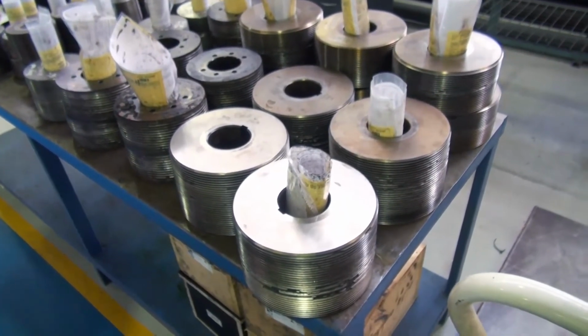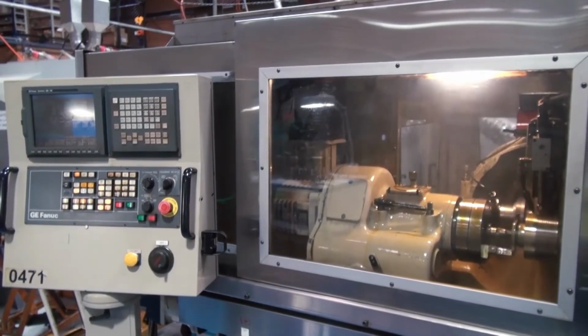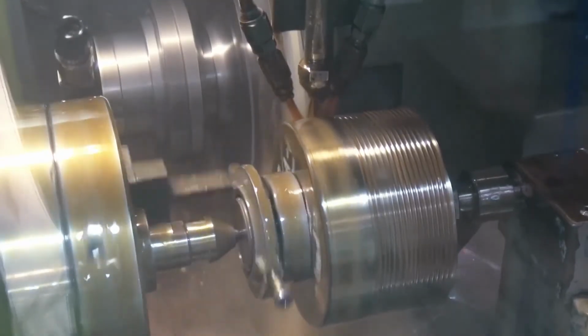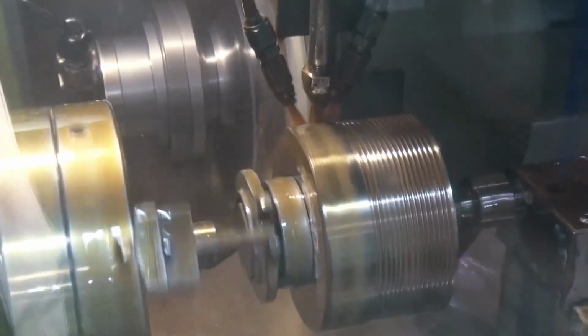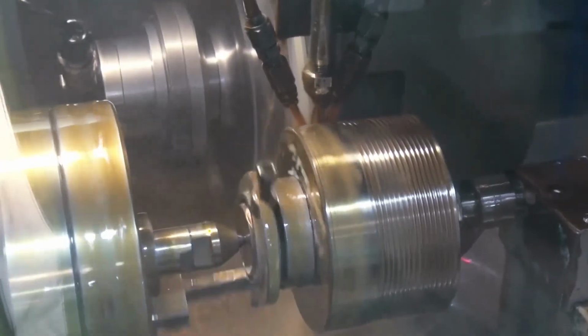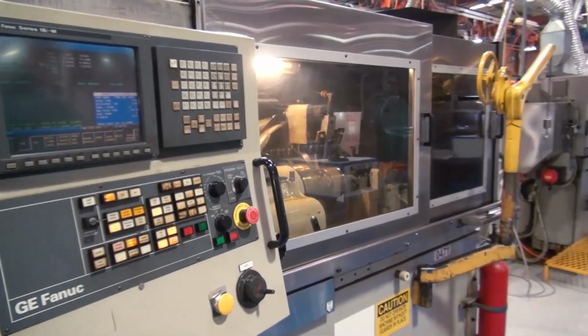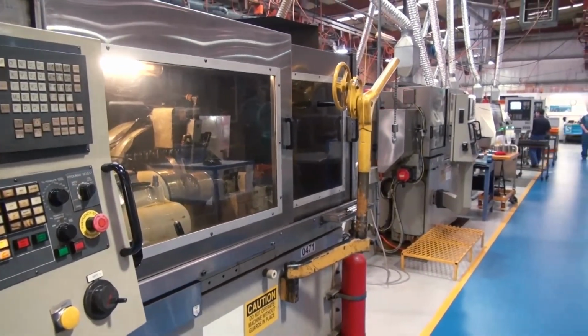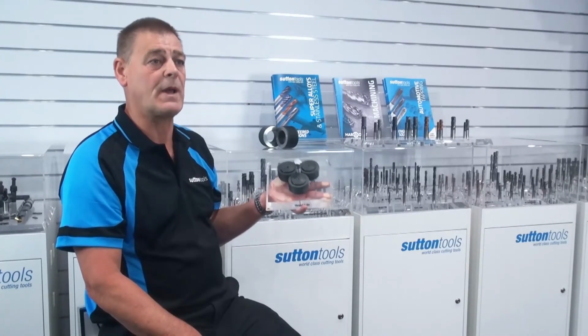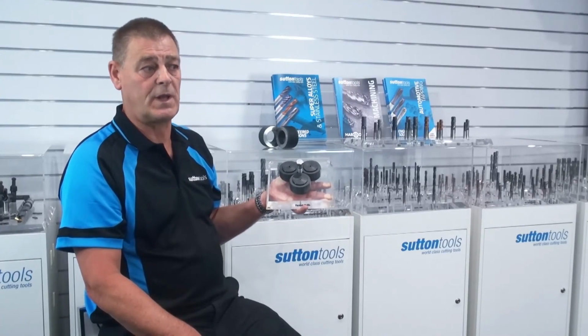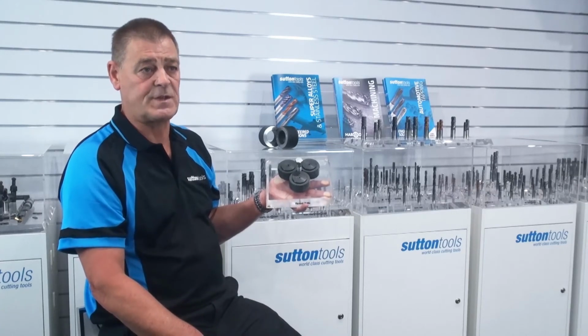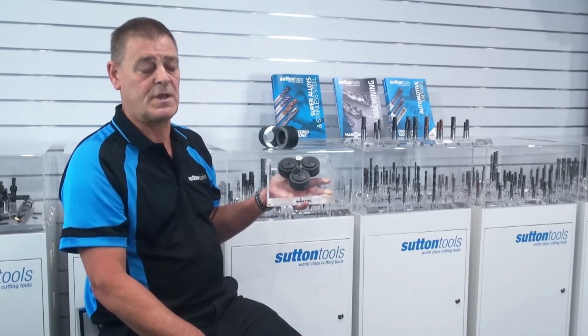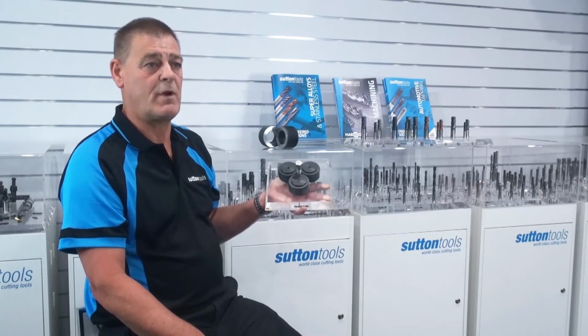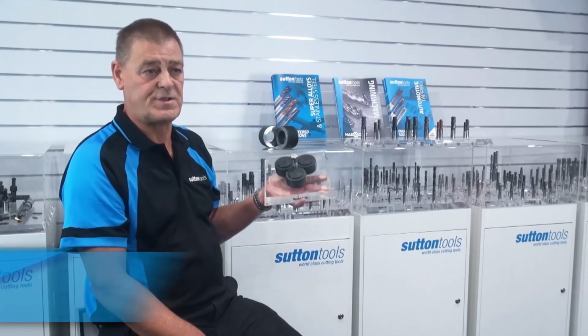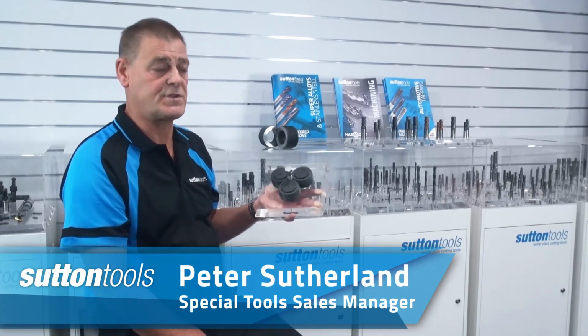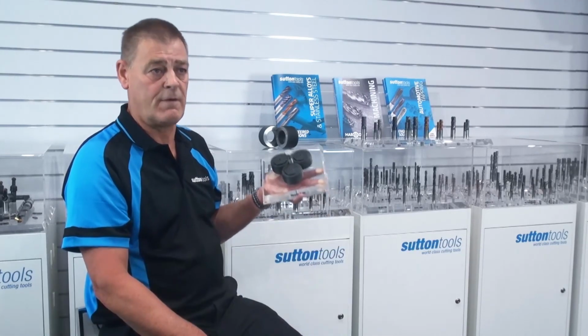The regrinding process involves peeling off the old threads, managing the diameter, pre-stress relieving, and then regrinding a new thread depending on the bolt diameter and pitch which needs to be rolled. And from that we can calculate the best optimum regrind process and what we can make that roll into. Regrinding is typically done in 2 working weeks and at less than 50% of the cost of a new roll. In some applications, we've been able to get up to 19 times single use roll life, which gives our customer or the end user very big savings.